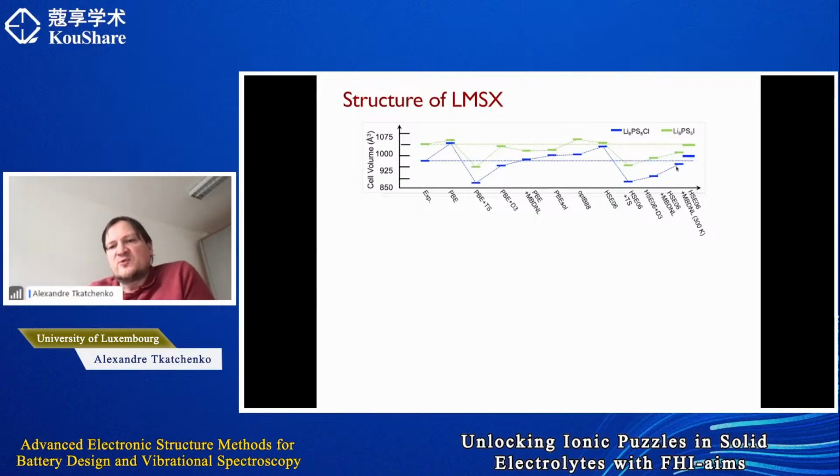Now let's look at the right, at the HSE plus MBDNL functional, which to me is really the only approach that includes the non-locality in both the exchange and in the correlation. And if you do that, you see that the results are getting actually pretty close to experiment, in particular if you go from 0K structure to 300K structure by including vibrational anharmonicity and zero-point energy correction. And you see we get results which are pretty close to experiment.